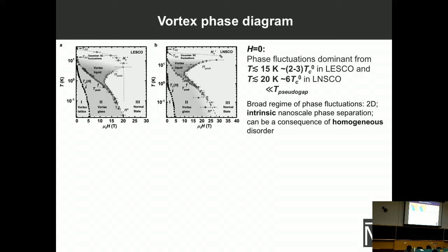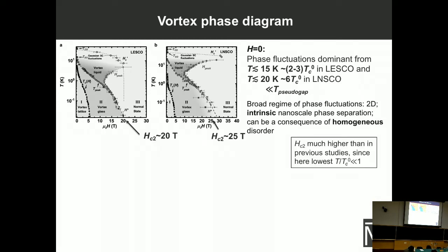And it is also known that even homogeneous disorder may give rise to spatially inhomogeneous superconducting amplitude in the material, and this has been observed in some cuprates using techniques such as STM. So the upper critical fields that we find for these materials are consistent with such a high temperature for the onset of the phase fluctuations dominated regime.